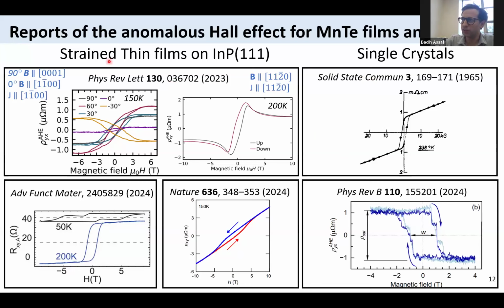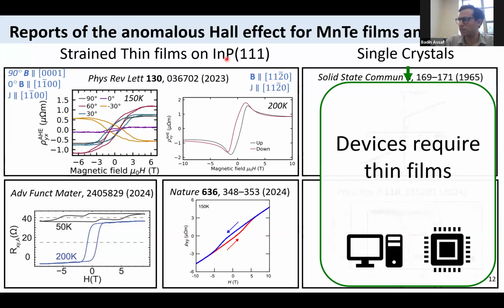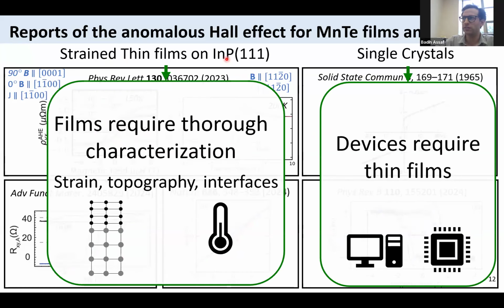But in thin films, most of what's reported is grown on indium phosphide, and as I'm going to show later, this synthesis on III-V substrates is actually a little bit subtle to understand because of the strains that are introduced in these films. So the bottom line is that there have been decent measurements on this material done in single crystals, but ultimately you need thin films to make devices. And if you want to make films, you really have to understand their strain, their topography, what happens when you put your material on an interface to really understand what's going on in an altermagnet.